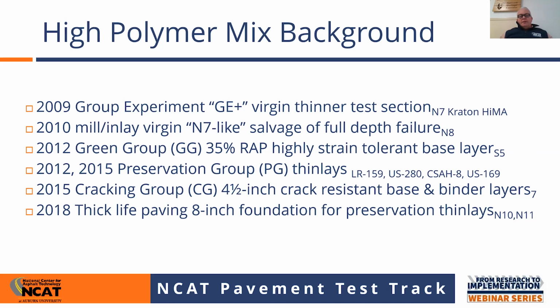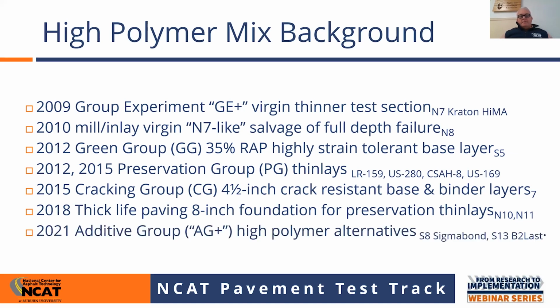In 2018, we did approximately 8-inch thick lift paving, 8 inches compacted thickness in a single pass, that we also built with HiMA binder using warm mix additive in sections N10 and N11. That's because we were studying thin lay performance in N10 and N11. So again, we wanted some deflections, but we wanted to not have any distresses from the underside that would confound the research. And that turned out very positive. Then finally in 2021, in an additive group plus test sections, we're evaluating high polymer alternatives. The alternatives are being studied in section S8, a product called Sigma Bond, and then in S13, a product called B2 Last. So that is the track background.